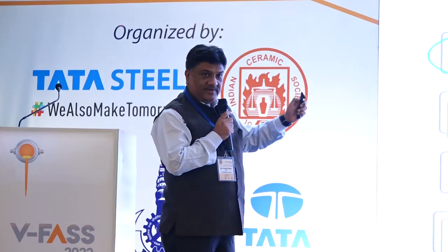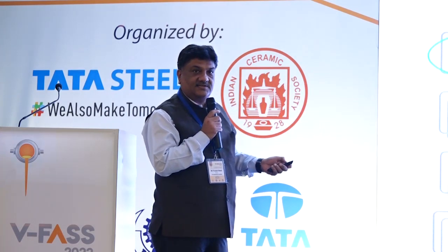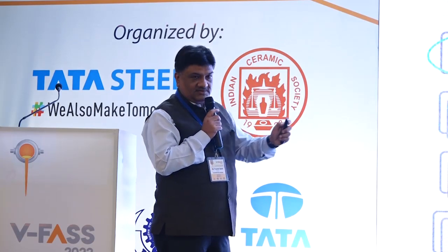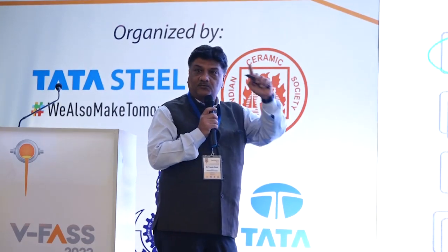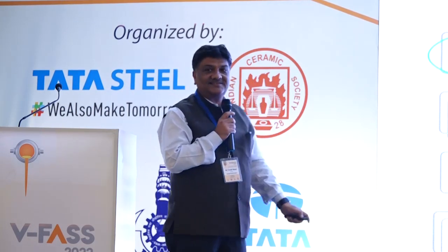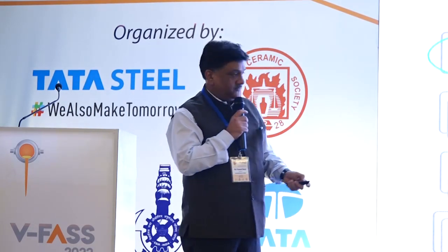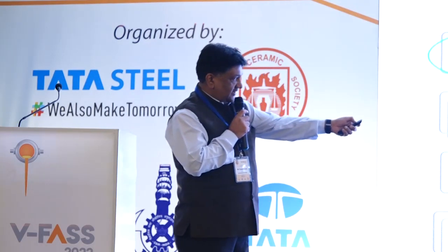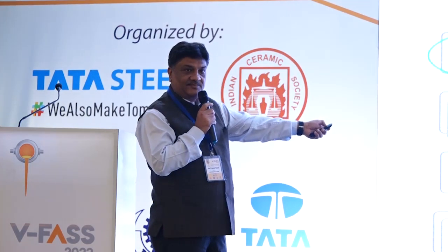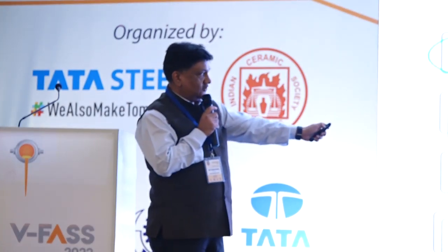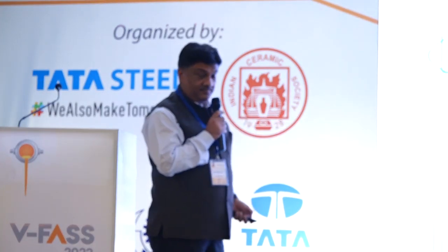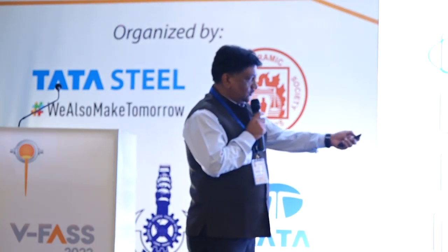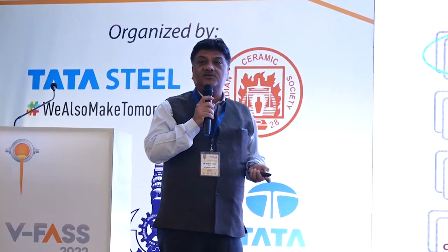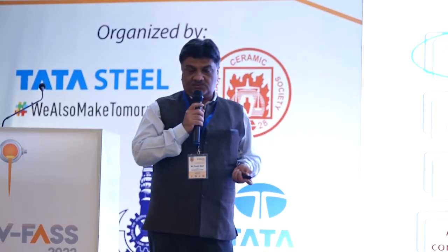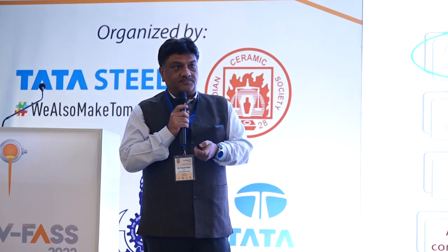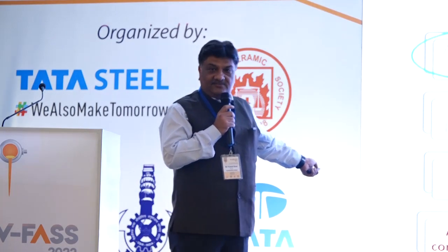What I would like to mention here is that we have tried this at Hazira, Surat, considering a monthly production of around 5,000 cubic meters per ready mix plant, because the main challenge is slag availability near the concrete producing plant. If I put some statistics on that, replacing with ACBF slag up to 30%, which is allowed, the code says 25%, but we tried it with 30% replacement of the total conventional aggregate, the consumption can be 1275 tons per month. So the major challenge to be addressed by all producers is where we can make this slag aggregate available.